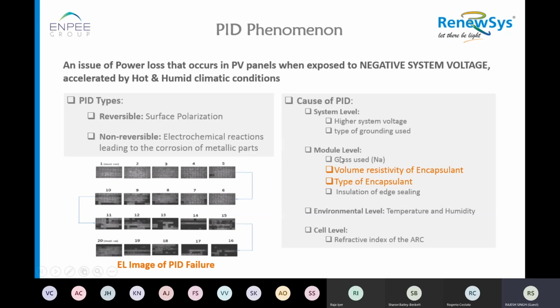PID is actually caused by various factors in the PV system, starting from the system level to the module level, to the environmental level, and finally the cell level. It is of two types, reversible and non-reversible. Reversible is just polarization during the day, and when you earth the module from negative system voltage, it goes away completely. But if the phenomenon continues for a longer time, an electrochemical reaction happens, which leads to corrosion of metallic parts, and then it becomes difficult for PID to get reduced.